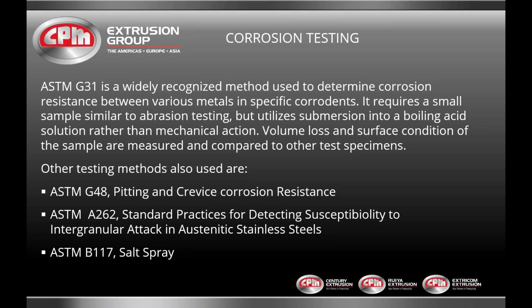Other test methods also used are ASTM G48 for pitting and crevice corrosion resistance, ASTM A262, standard practices for detecting susceptibility to intergranular attack in austenitic stainless steels, and ASTM B117 salt spray. Typically we use ASTM G48 and or ASTM G31. We have used A262 for testing intergranular attack in austenitic stainless steels, but we've already performed those tests, so we have the results.